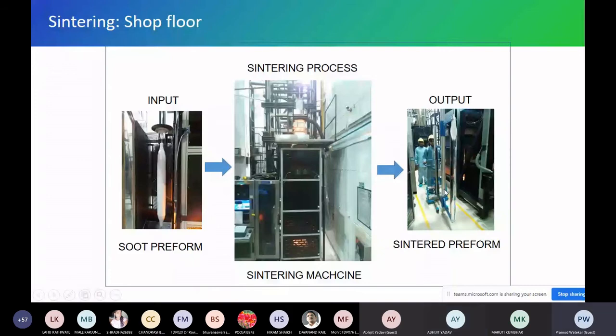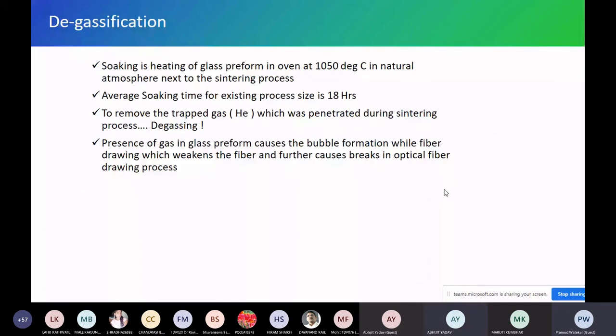One more thing is degasification, because while converting that soot into glass, we are giving helium and chlorine. Chlorine will go out anyway. It's not harmful for our glass. But helium can get trapped. If helium is trapped, it makes bubbles. We are using helium actually to remove the bubbles, but it may be possible that it has the opposite effect. Generally, some trapping takes place at higher gaps, more than 500 micrometer, where helium can get trapped and form a bubble. So degasification is done, which is just simple.